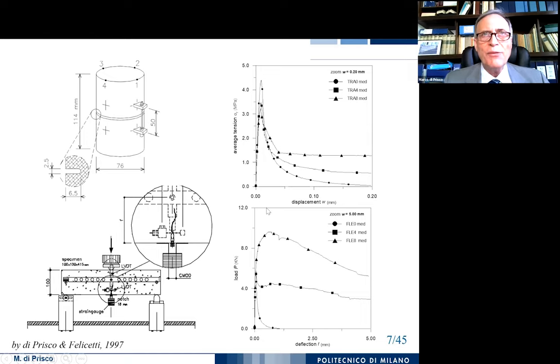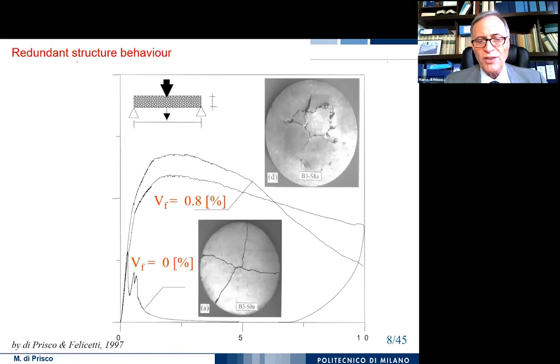But this seems like nothing if we look at the uniaxial tension. When we analyze the same material in bending, for instance, we see a huge difference between a plain concrete, which is practically completely brittle, a material with only 30 kilograms of steel fiber, so 0.4% in terms of volume percentage, and the material with 0.8%. So you see how in bending, due to the redistribution of the stresses in the cross-section, you could have a very important contribution from fibers. This contribution increases with the redundancy